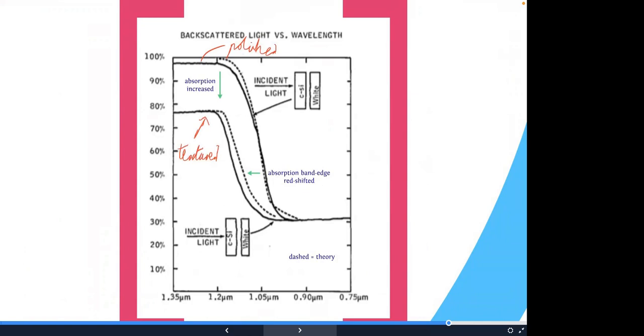The other thing that has happened is that the absorption band has redshifted, which is actually a good thing in the case of silicon, because you're pushing the band of absorption into the regime that is more efficiently absorbed by the silicon solar cell. Now, by the way, this is a spectrum, it's not a number. So this integrating sphere also resolves the spectrum. That's where the band edge is important.